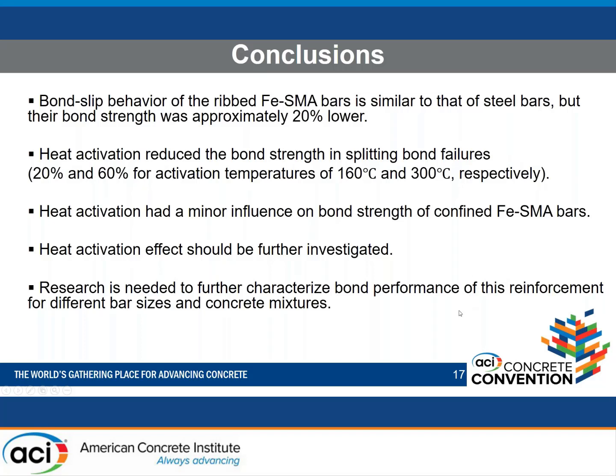So to wrap up, the bond slip behavior of ribbed SMA bars, iron-based, obviously, was similar to steel bars. The bond strength, however, was 20% lower. For the heat activation influence, we had major influence for unconfined specimens that reached 60% when the activation temperature is 300 C. While for confined specimens, we don't have that influence. They showed very similar behavior. And for that reason, the heat activation effect should be further investigated later. Also, research is needed to further characterize the bond performance for different bar sizes. Again, we used the 16 millimeter bar here. We need to check other bars, and different concrete mixtures.